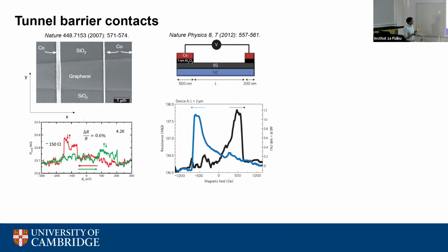And this is what I was saying, you can apply a magnetic field and you measure the resistance. And when the spins flip, you can see a resistance peak due to the anti-parallel or parallel orientation of these two ferromagnetic contacts. And you measure a magnetoresistance around 1 to 2% across a graphene channel. And in this case, they use a 1 nanometer aluminum oxide tunnel barrier to act as a tunnel barrier for spin injection. Again, as I said, when you make devices with 2D materials, you have to take care of their nature and cannot just mimic what other materials have used.